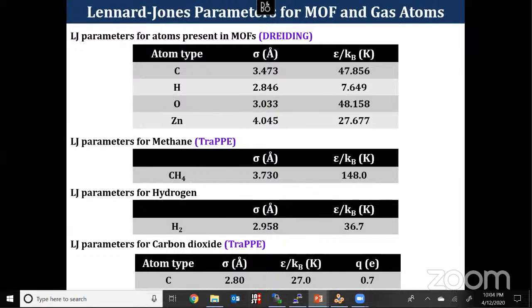Then we moved on to quantify whether this model MOF will adsorb a gas molecule in bulk amount, or whether it has any drawback or not. In order to do that, we need to have the Lennard-Jones potential parameters, sigma value as well as epsilon value. So here I have used methane, hydrogen, as well as carbon dioxide. Methane and hydrogen are treated with a united atom approach.